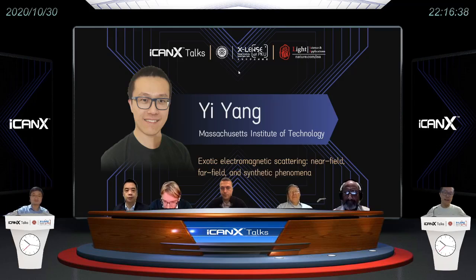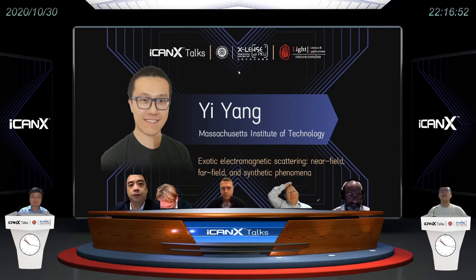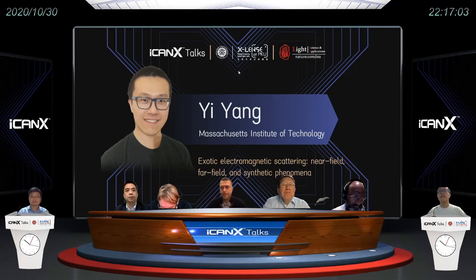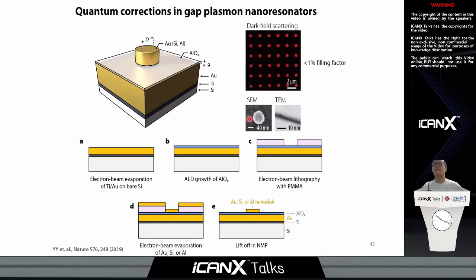Oh, thanks. So I'll first answer the first question. Yeah, you can see here, indeed, this nanodisk resonator is not a perfect sphere. And in our experimental measurement, we adopt a depolarized excitation. Therefore, we effectively excite an average dipole moment along an arbitrary orientation along this nanodisk. This is the reason why we choose to work with a nanodisk rather than other structures, because it's less sensitive to the polarization change. And since we use depolarized light, the averaged diameter of the nanodisk serves as a nice parameterization of this overall effect.